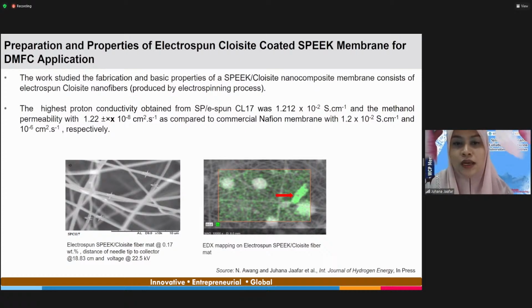As a summary of the main properties of our developed membrane, we obtain a comparable magnitude of proton conductivity to that of commercial Nafion membrane and significantly lower methanol permeability. As you can see here, our methanol permeability is only 1.22 times 10 to the power of negative 8. Meanwhile, the commercial Nafion membrane is 1.2 times 10 to the power of negative 6. So it's like 2 orders different.